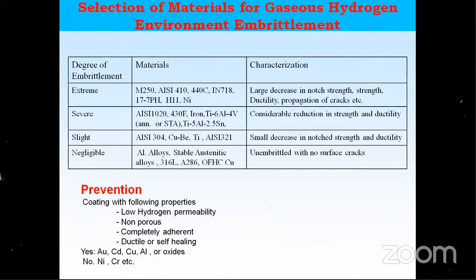In fact, based on these first principles, I have developed a material. It is yet to be used. It is one of my pet developments which I have done in NPC, which I'll discuss later in this presentation. Prevention: gold, silver coating, cadmium, aluminum, all these things are very good. The coating should have low hydrogen permeability, be non-porous, completely adherent, ductile and self-healing. This kind of coating can help. Nickel and chromium cannot be used for this application.